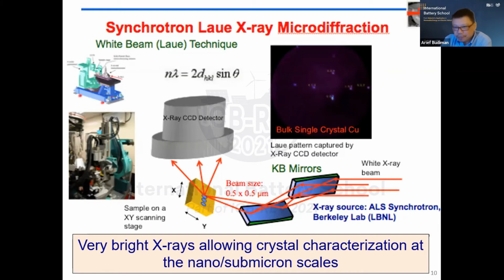But it's basically where the particle physicists are accelerating electrons in a circular way, because only when it is circular can you keep accelerating the particles. But as a byproduct of it, we have X-ray radiation. And the X-ray radiation turns out to be very useful for materials science, in terms of being very bright, orders of magnitude higher intensity than a normal lab X-ray. Because of that, we can focus it down to very small. So now I believe it is already at the nanometer scale. It's like you have an eye that can see a resolution of about 50 nanometers at this point in time, I think.